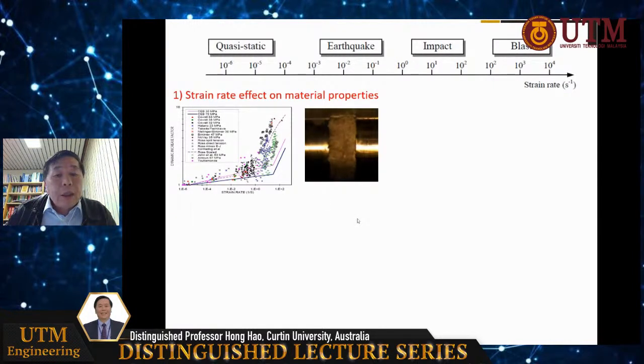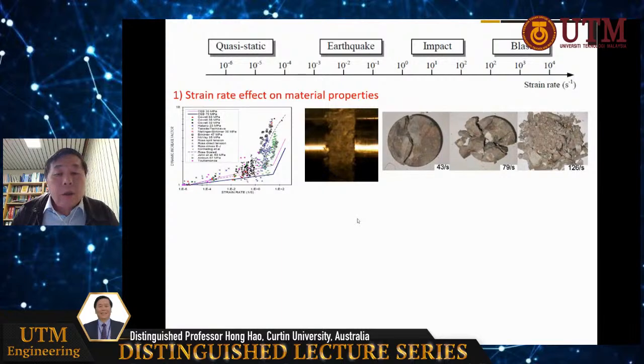For example, the reason it changes material properties, I showed this one, the different impact speed, different loading rate, the damage modes are different. Thus, you see at a very high, very fast impact, this concrete specimen will be completely smashed, fragmentized. What you get is just ashes if you impact very fast. But if you apply a static load, what you get is just a very predominant failure surface, shear failure or through vertical cracks. So the damage modes are different. That's why the material properties you get will be different.